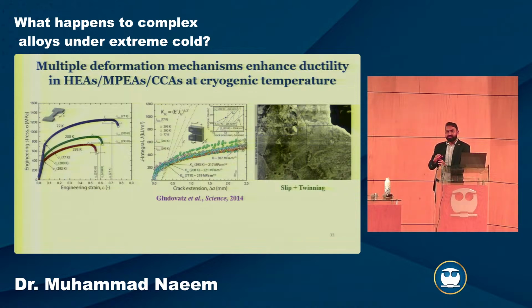Usually they don't show an increase in ductility, but it was surprising that at 77 Kelvin there is not only an increase in strength, but also a significant increase in ductility. It maintained its fracture toughness. This was work from Rob Ritchie and Easo George, people from Oak Ridge and Lawrence Berkeley National Lab. They associated this increase in ductility and strain hardening with deformation twinning. At room temperature it had only dislocation slip, but at low temperature it also had twinning.